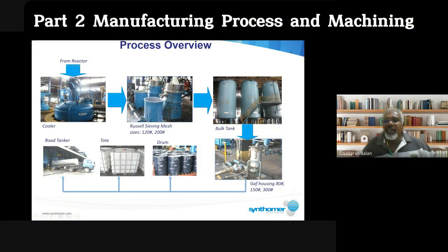This is a filter on your right, bottom right, the GAF filter. We put filter bags inside this. The filter bags have different sizes: 40 mesh, 80 mesh, 150 mesh. This depends on the quality testing, they will advise how bad it is, because this finished product emulsion will normally have grit inside, some unreacted chemicals. So these unreacted chemicals we have to filter out before we do the packaging. The packaging will be in these drums. This is a 1 ton, 1000 kg container, we call it IBC container, and on the far left is the road tanker. Normally going overseas will go in IBC or drum. The local ones, mainly for coatings, will go in road tanker.